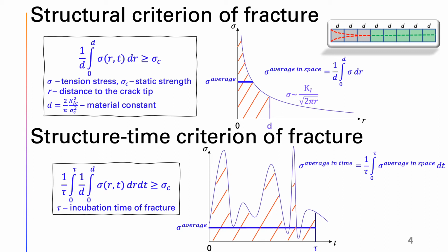The structure-time criterion is an extension of the structural criterion, and it considers the mean value of the stress variations both in space over the structural block of size d and over time of duration tau. Tau is an incubation time, which is a characteristic time of fracture. It's supposed that fracture is not an instantaneous process, but on the contrary, the material needs time to prepare for it. This parameter can be found using an analytical approximation to the experimental results, and it's a material constant as well.